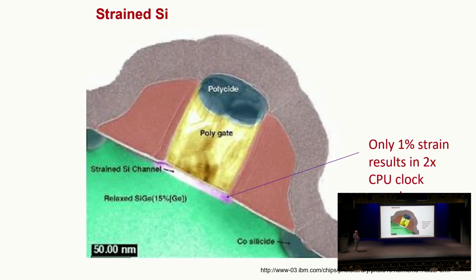The motivation behind this started in the 1980s at Bell Labs, and Intel manufactured so-called strained silicon. This is a picture from IBM, and what you see here is a strained silicon channel, and you can see the scale here. This is 50 nanometers. In the computer chips that were being made starting in the 90s, this strained silicon channel with only 1% strain could result in a 2x improvement in clock speed and performance.